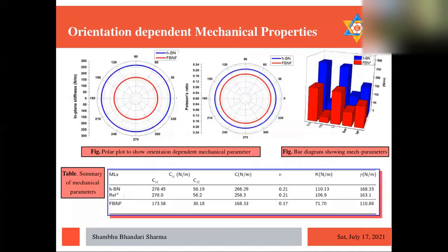And here is the orientation-dependent mechanical properties. We plot the polar plot there for in-plane stiffness and Poisson's ratio. And we can see the perfect circle for both monolayers, confirming the fact that these both monolayers are mechanically isotropic.